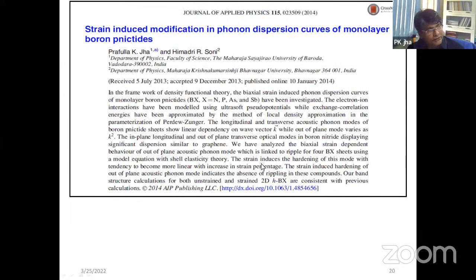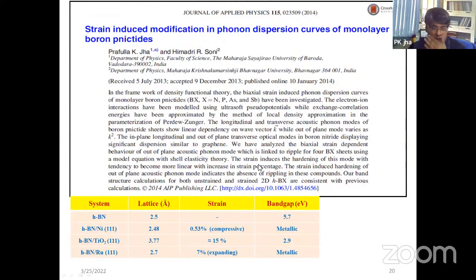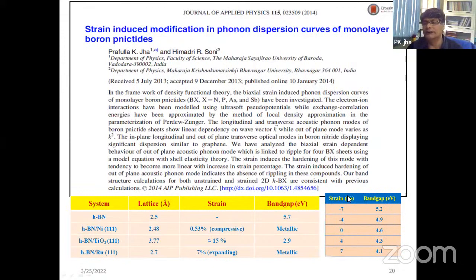So you can see the different phonon dispersion curves for different boron nitrides in different cases. The phonon dispersion curve also can be tuned by applying the strain, and that basically the strain is useful in tuning the band gap, right? Our study is a theoretical study, but in the experimental one you can see that by having the strain, of course, there is a change in the lattice parameter. This is the strain percentage, because this is an experimental study, and you can see that the band gap varies. And that is what we also found in our studies, that for different percentages of strain, you have a different band gap. So band gap can be tuned by applying the strain.